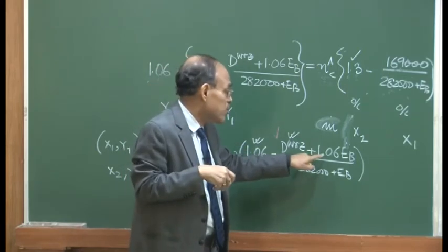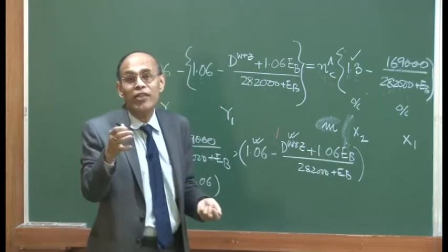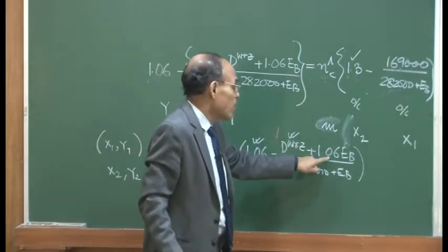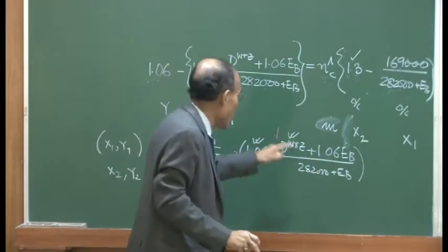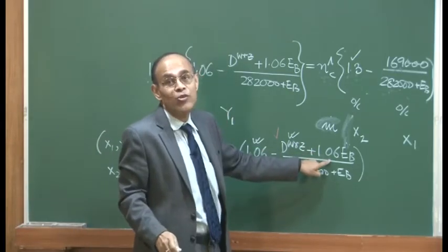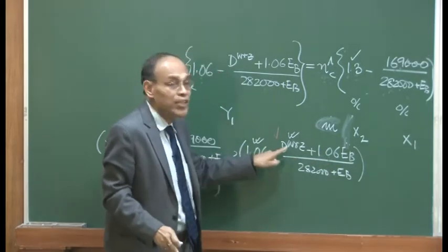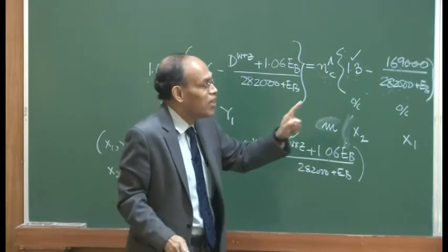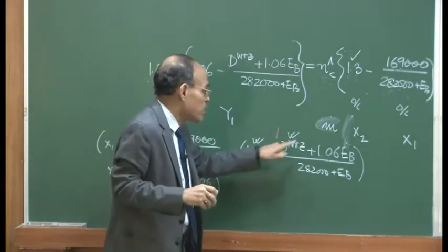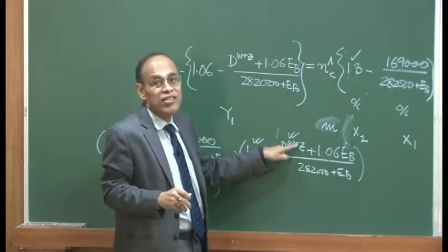So, in that particular case, O by Fe ratio in the ore material is going to change. Similarly, if the ore contains silica, MnO, P2O5, etc., 1.06 will change. So, for all blast furnaces, do not use this particular prescription. Try to calculate what is that 1.06 applicable for your scenario. What is that applicable dWRZ? Do not put 330,000 and try to draw a graph for every blast furnace itself. For every blast furnace, the factor 1.06 is going to be different. For every blast furnace, dWRZ is going to be different.